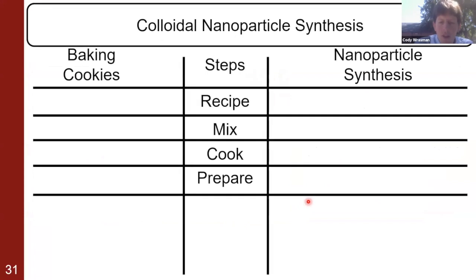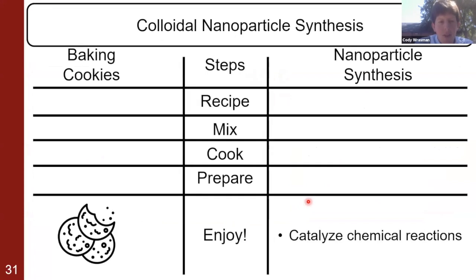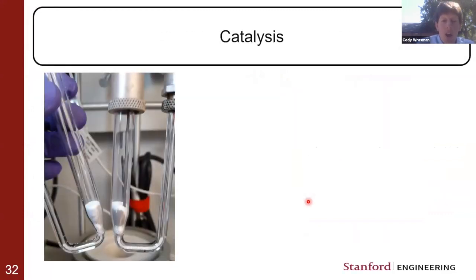Once you've gone through all of the work to make your catalyst or to make your cookies, the final step is just to enjoy them. In catalysis, that would mean using them for chemical reactions. We run our reactions on relatively small scales. I'm showing you our catalytic reactors here. They're these glass U-tubes, where this small amount of dark powder is the catalyst powder that we've been making in these previous steps. We used maybe up to 100 milligrams of catalyst powder in each test.